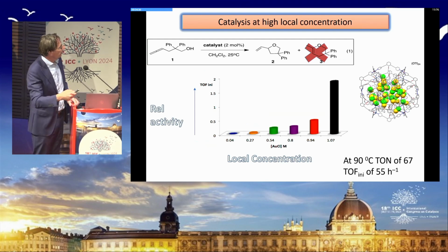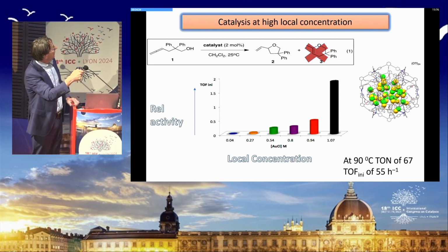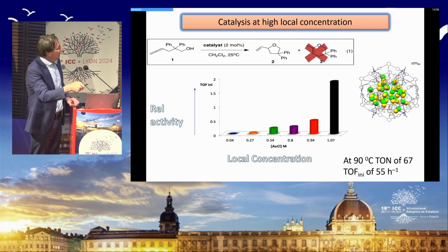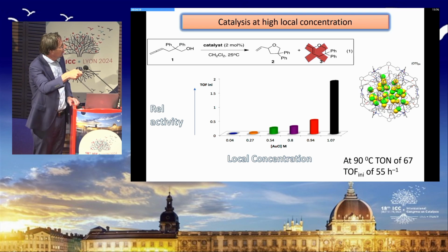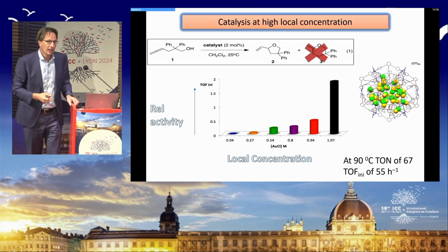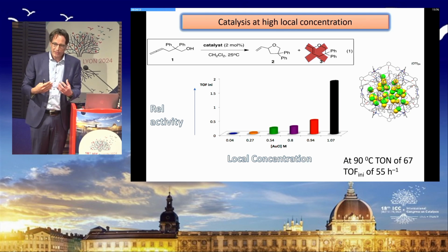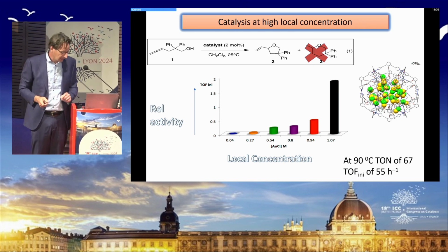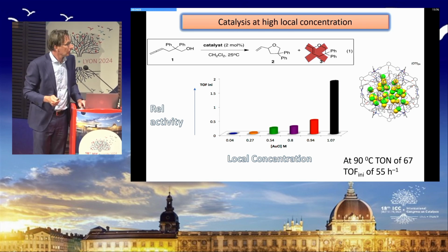And as a first example, he looked at the cyclization of this allyl alcohol to form this 5-membered ring, and we plotted the relative activity as function of the local concentration, because we can dilute by mixing in building blocks. And as you can see, the higher the local concentration, the higher the reactivity. And we think we understand that because at this 1 molar local concentration, we get gold-gold interactions, and therefore the active species is a di- or multi-gold complex.